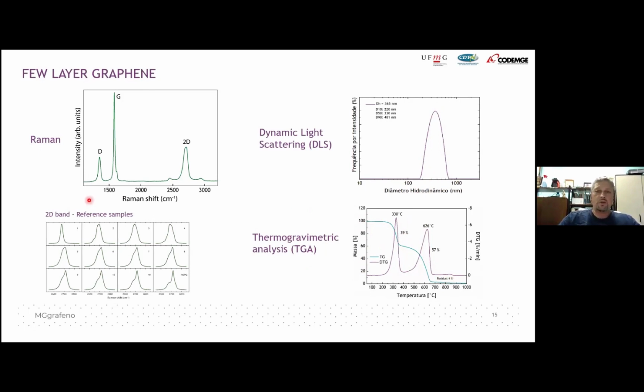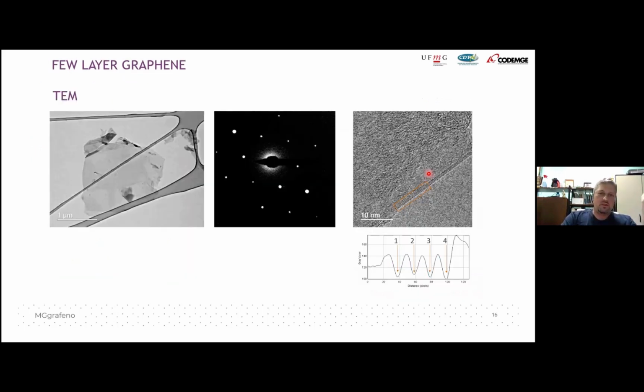Okay, if I look at this picture here, I just measured this from the liquids, from the solution, the suspension. I would say that this peak here gives me something around 4 to 5 layers. This is what I would say about the shape of this peak, and I would say that my diameter, the diameter of my graphene, is around 300 nanometers. Okay, so this is what I already showed.